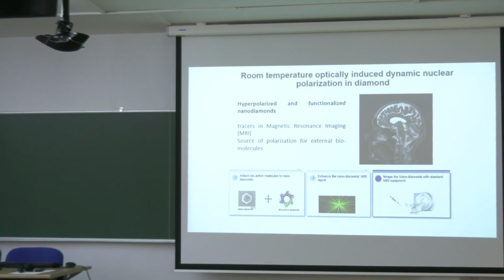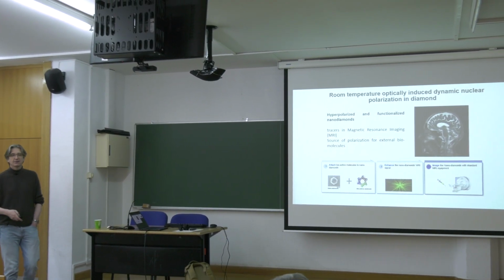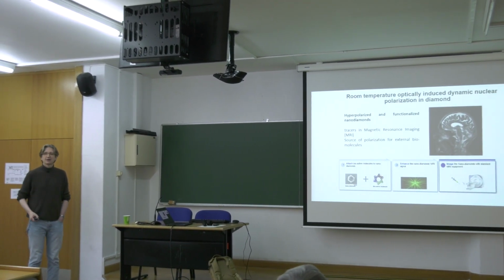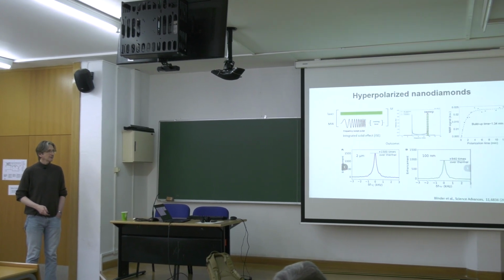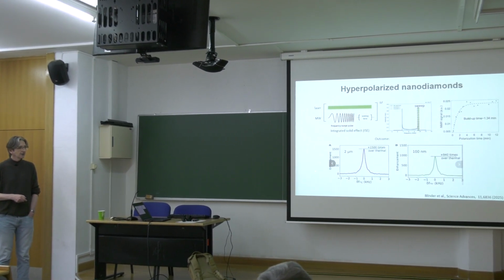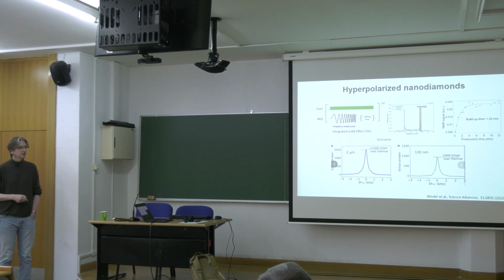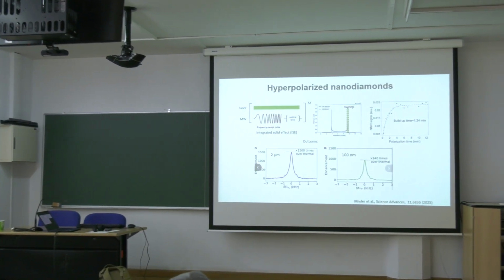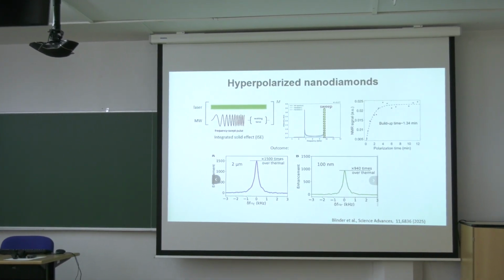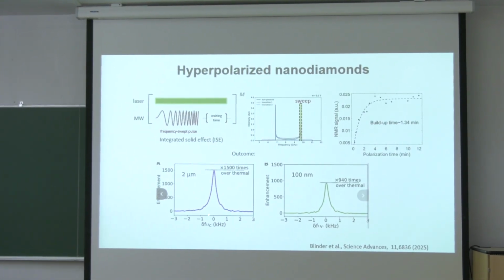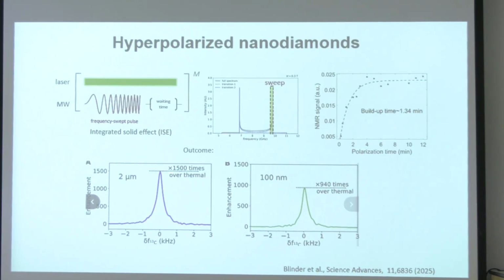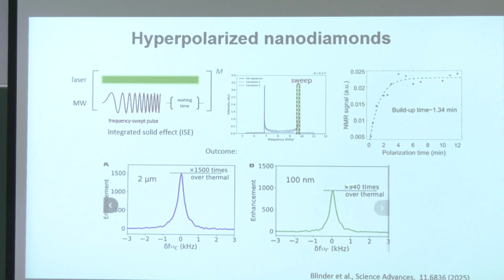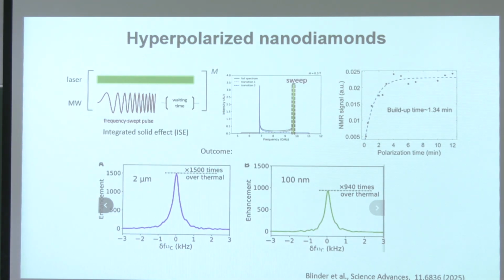At the moment, it's only possible to do an animal experiment and get much sharper, much stronger signal in MRI machine. And so I think I skip this and just show you the example of this that in micrometer size and submicrometer size nanodiamonds, we can increase the NMR signals, which is the basis of this MRI imaging, by a few thousand times for micrometer size diamond and about 1,000 times for a submicrometer size diamond. And this technique can be used in future for example, imaging nanodiamonds as markers inside of MRI.